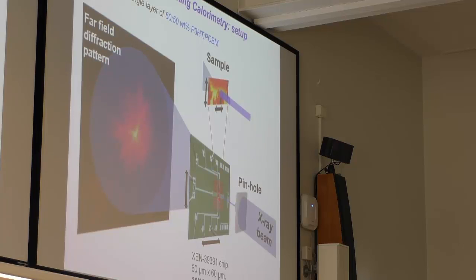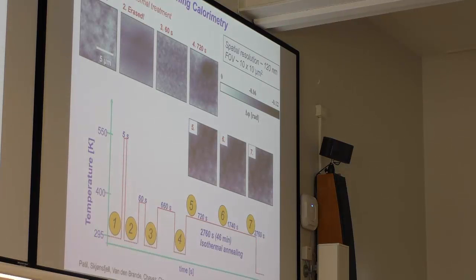of sample sitting here, right? And the diameter of the incoming X-ray beam is a few micron, so that we are able to scan across this sample. And as I said, there are interdigitated sensors, the thermocouples, to keep control of the temperature. And because of all this, we could do experiments, right? So the idea is that the first thing that you see here is the as-cast structure, meaning that the polymer blend had been dissolved in a solvent and deposited onto the silicon nitride membrane, and then the solvent evaporates, of course, and you are left with a thin film.